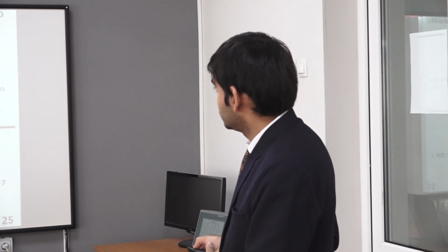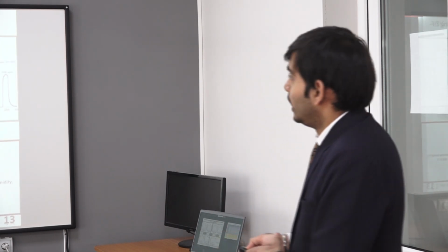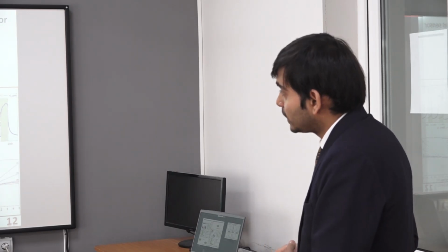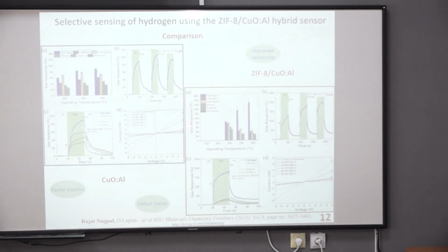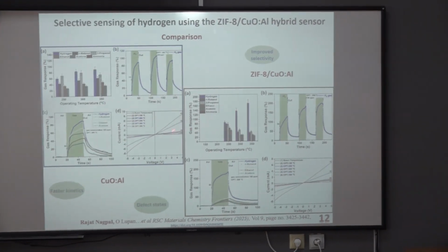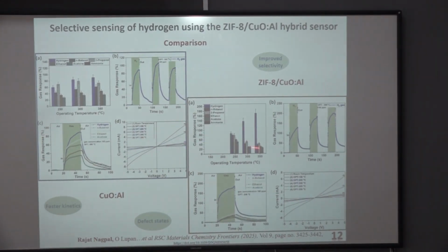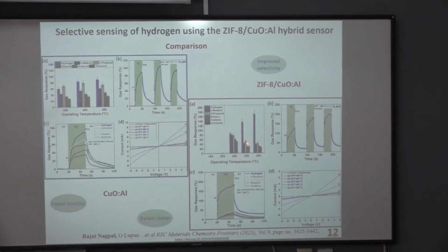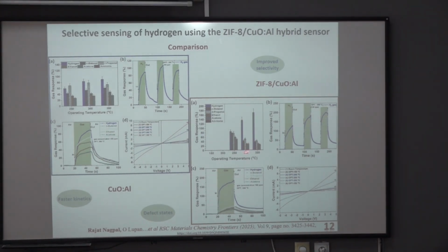If you will see ZIF8 based results, appreciable enhancement in selectivity for hydrogen can be observed for the ZIF8 case, and also high sensing response for other VOCs. But among VOCs, we observe n-butanol shows high sensing response, and among all, hydrogen.